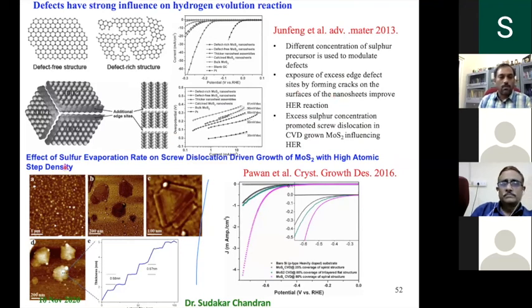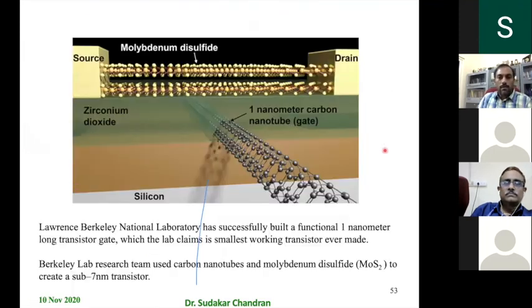And people have also shown, for example, that when you grow them by the CVD method or some other method, sulfur evaporation can enhance the screw dislocation. These are the pyramid-like structures I discussed earlier, something similar. So it increases such dislocations. So there is a way to control the defect concentration in this.